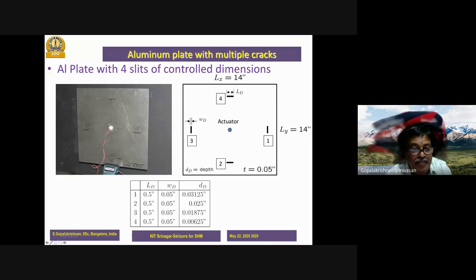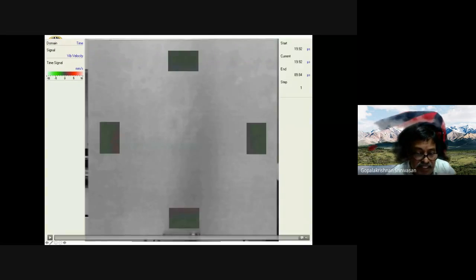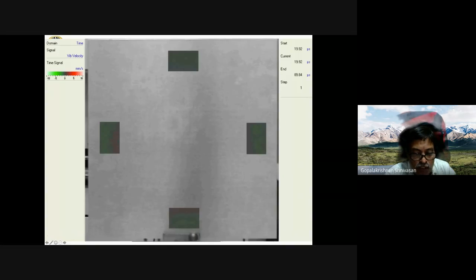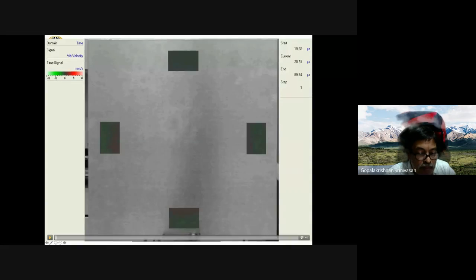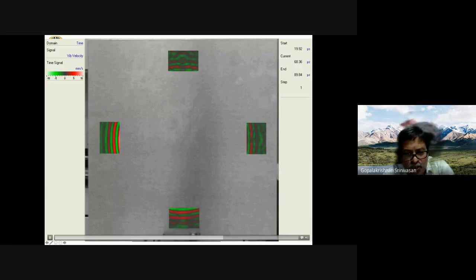Okay, and this is the video of the actual measurements taken at these 4 regions that were monitored. You could see here, when it hits the crack, suddenly you can see what is happening, very low. Here when the crack is there, more coupling is taking place, but here the crack levels are so low, you can't see that, whereas you can see here.